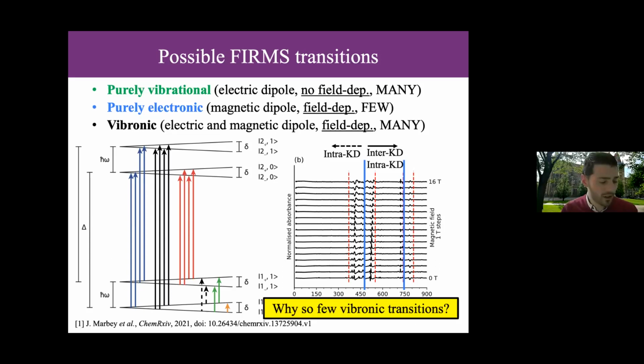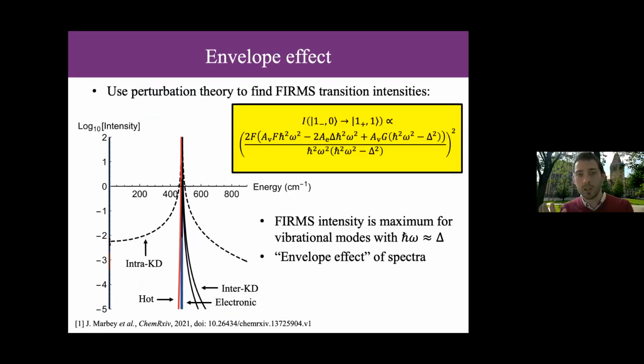And I'm running short of time, so I'll just move quickly through this. But basically, if you use perturbation theory, you can show that the intensity of a FIRMS spectrum gives you this divergence in intensity in first order perturbation theory when you have vibrational modes that are close in energy to your first excited state. Now, I'm not saying that you are absorbing that vibrational mode. Remember, these are not absorptions of phonons or vibrations to make the excitation. We're driving a combined electronic and vibrational excitation with an optical photon. So we're not absorbing a quantum of vibration to make an electronic transition, but we're driving both an electronic and vibrational excitation via a photon.